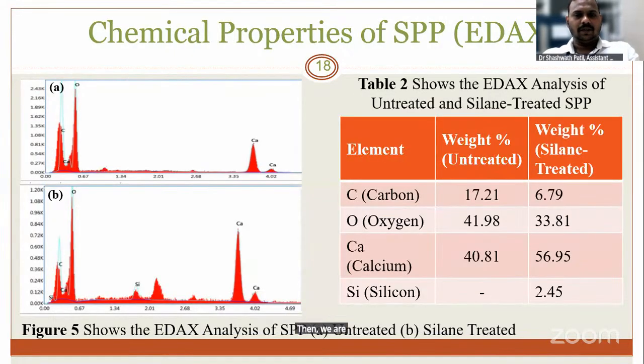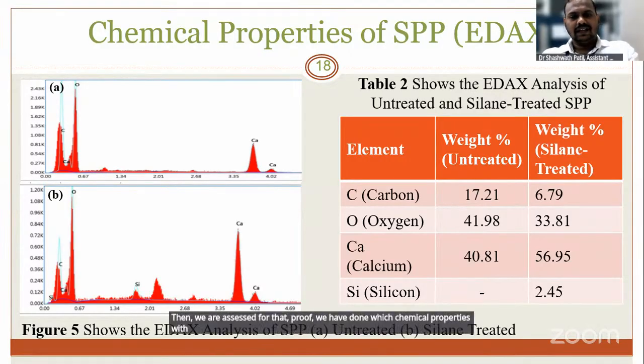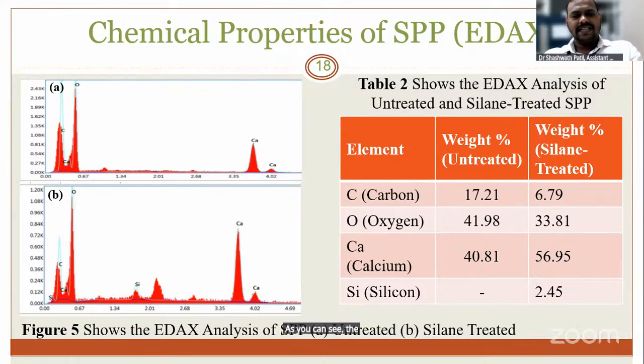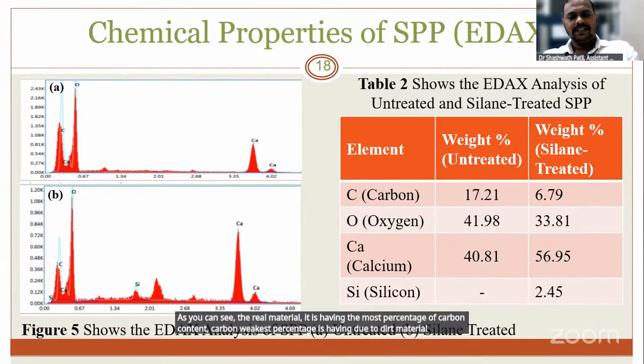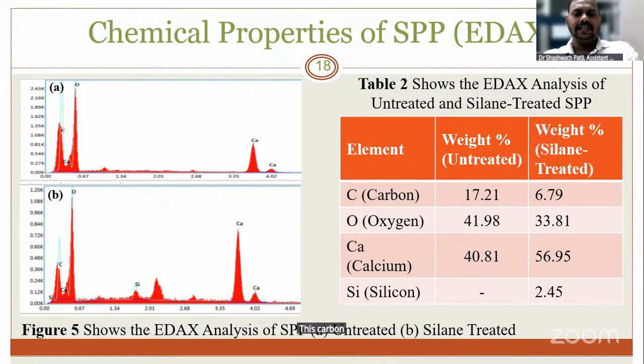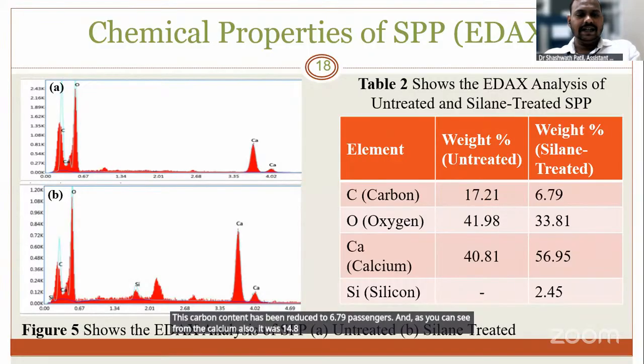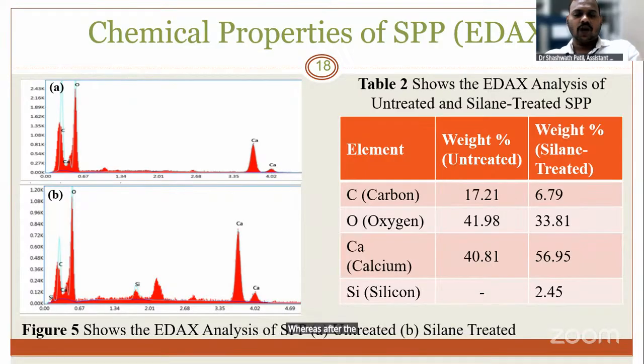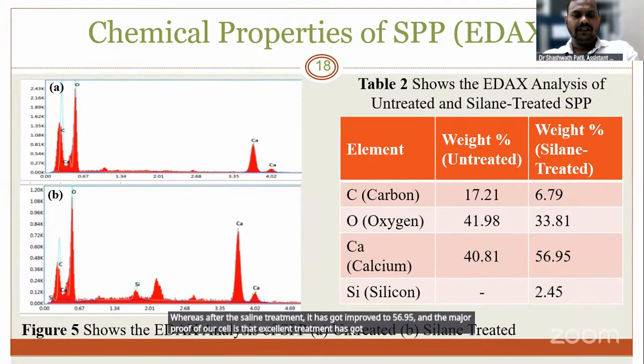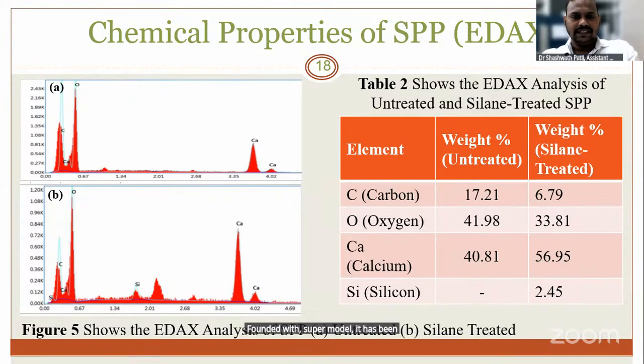Then we tested for proof. We did the chemical analysis with EDAX. As you can see, image A shows the EDAX analysis of the untreated sample and B shows the silane treated one. In A, the material has a higher carbon weight percentage due to dirt and so on. Since we used the silane treatment, this carbon content has been reduced to 6.79%. Calcium was 40.81 in the untreated sample, whereas after the silane treatment it improved to 56.95. The major proof that the silane treatment has bonded with the squid pen is in this EDAX analysis, as you can see, the silicon has been attained from 2.45%.